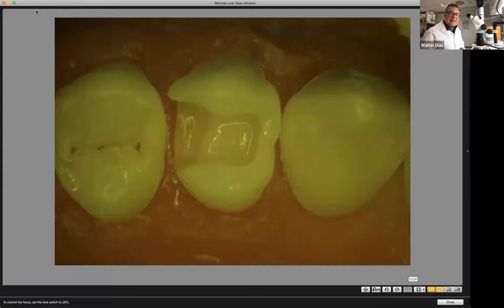I mean, let me show you how much 5 seconds is. Yeah, let's go. 5 seconds is... That's 5 seconds. It's a long time, you know. But if you stick to the minimal required, and you try to lightly dry the adhesive for 5 seconds, the quality of your adhesive technique is going to improve exponentially. So this is a great tip that I'm giving.